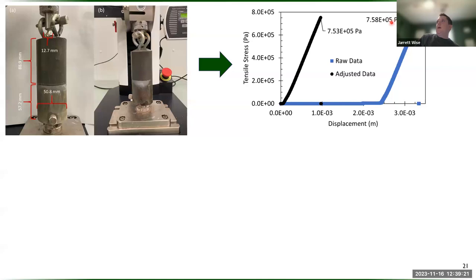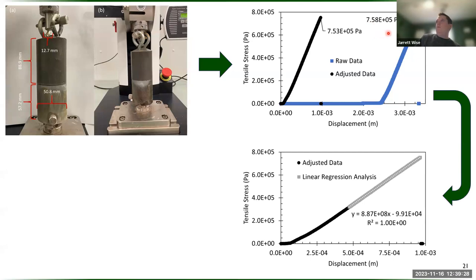And you see that the max stress is roughly 0.8 MPa. But if you really look at it, this is a really linear line. You can see the trend line matches up 100%. So what this shows is that the cement to steel bond does have an elastic range on it. It does pull apart but come together until you hit this failure point.